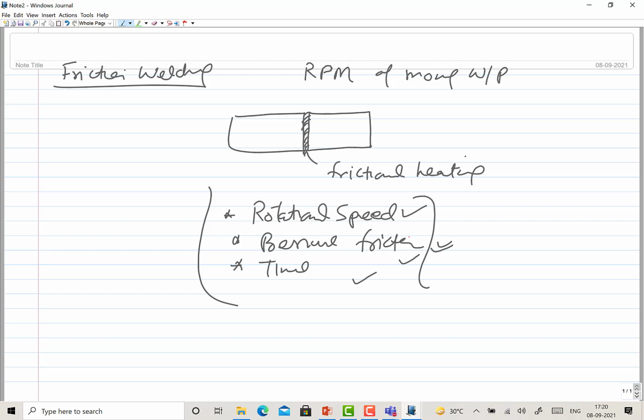Why? Because let's say you need a temperature of 800 degrees centigrade at the interface. So frictional heat, maybe you can generate at the rate of 2 kilojoule per second, or 0.5 kilojoule. So it depends on what you can generate, at what rate you can generate, and that will be a function of the rotational speed, friction pressure, and the time. So at what rate you are generating. If you are generating at lower rate, you need longer time.